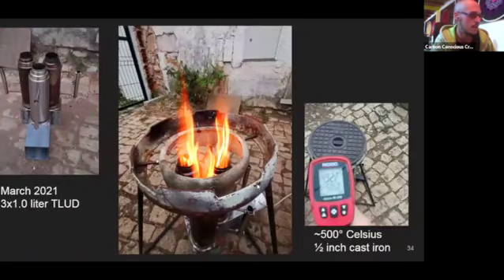And then I made a base with 3 of the 1-liter T-LUT gasifiers. And as you can see on the bottom right picture, the picture is a bit vague, but it reads 492 degrees Celsius. This is a cast iron sewer lid of half an inch. So that got incredibly hot with just 3 of those little burners.